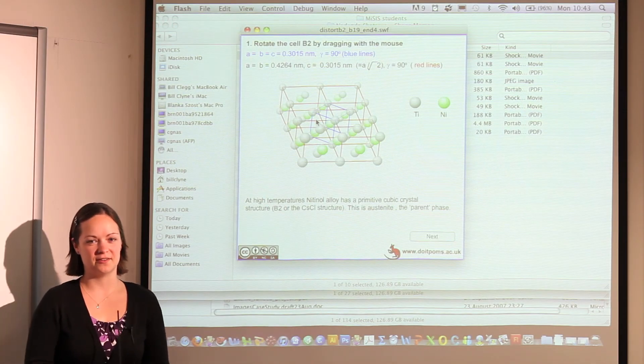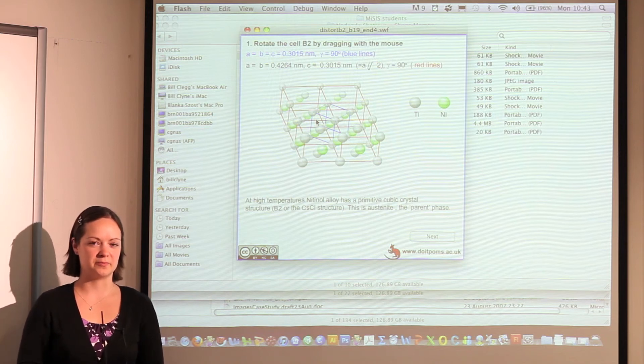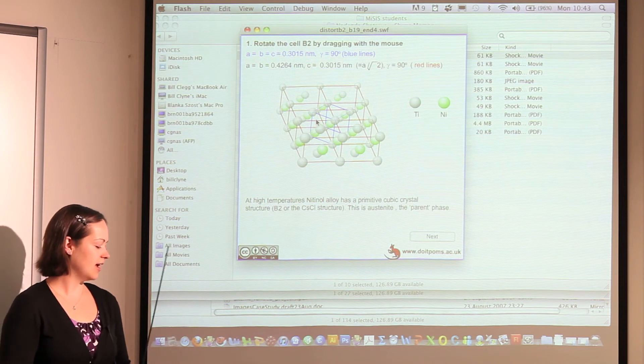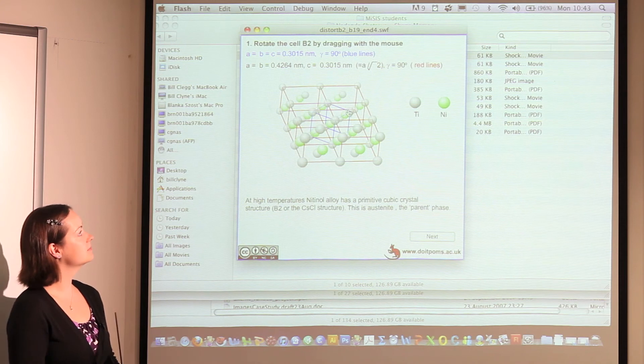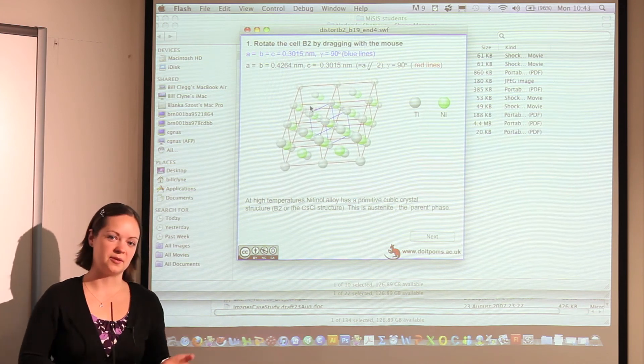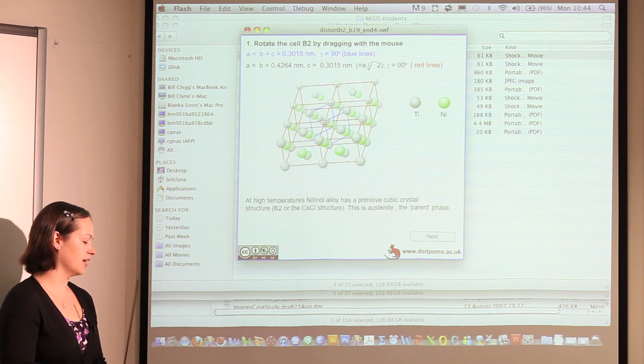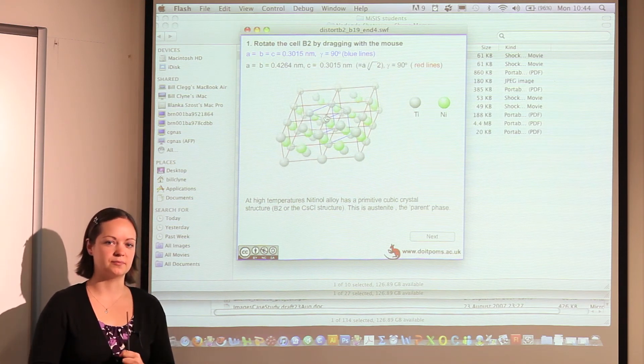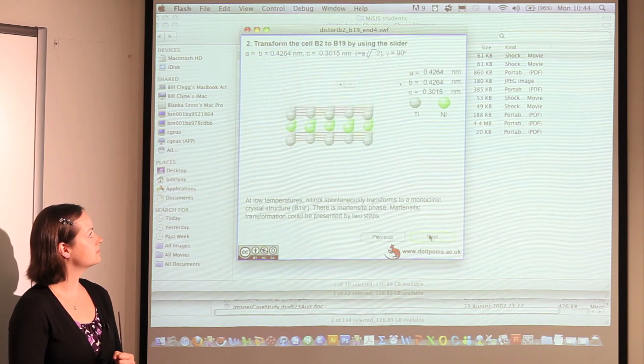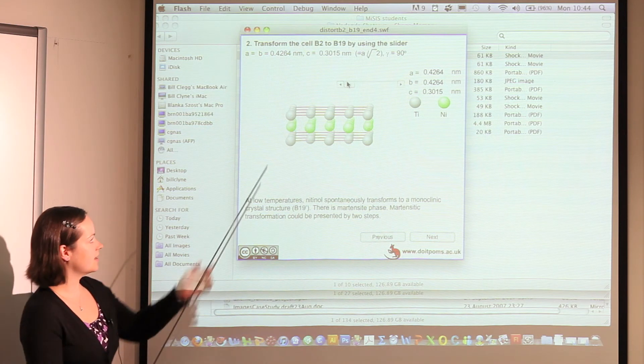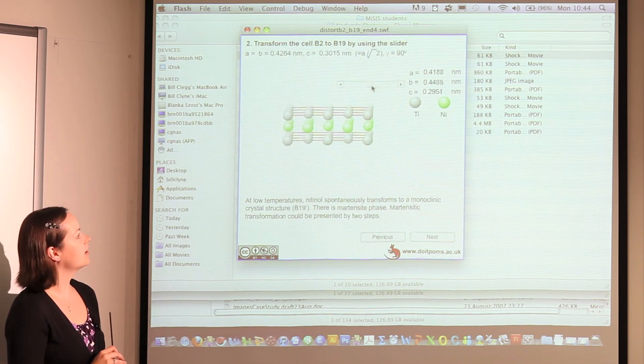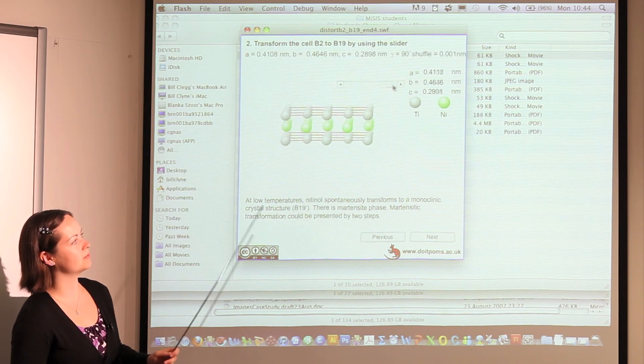This animation shows the crystal structures of the austenite and martensite phases, and illustrates how the phase transformation occurs between the two. This is the high-temperature austenite phase — it has a caesium chloride structure, and the cubic unit cell is shown in blue here. An alternative way of describing the structure is in terms of these red unit cells, which are tetragonal, basically because this allows us to see the transformation more easily. By dragging the slider, we can show what happens in the first stage of the transformation, and you can see that it changes into an orthorhombic crystal structure.